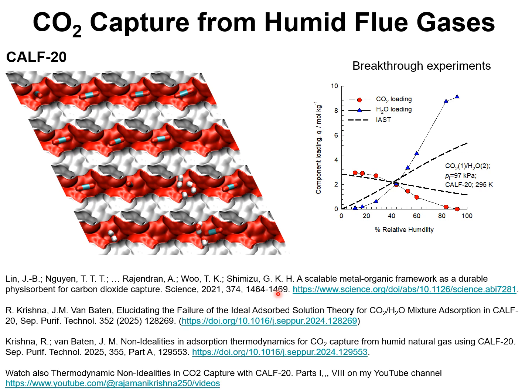This Science paper reports experimental data on the influence of moisture on the loadings of CO2, from breakthrough experiments. The experimental data on the component loadings of CO2, indicated by the red circles, and water, indicated by the blue triangles, have been presented as a function of the percentage relative humidity. If we compare the experimental data determined from breakthrough experiments with those estimated from the ideal adsorbed solution theory, we note that there are significant deviations from the IAST estimates.